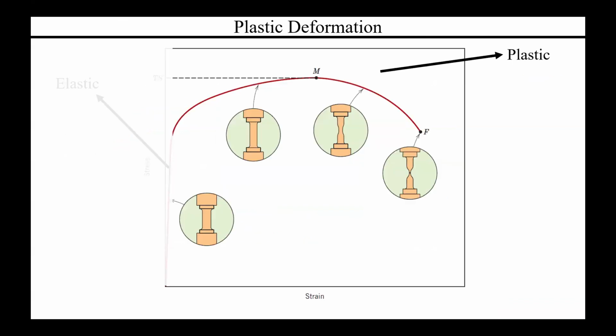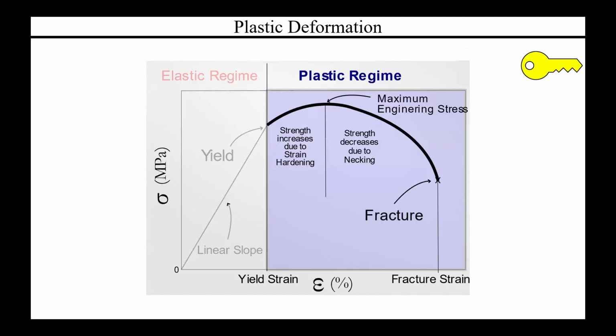So now let's move into the plastic region. The plastic region can be broken up into a few different zones. The first is, you've left your elastic region and you're pushing yourself towards this M point, or tensile strength. We'll talk about it later. That is where you're seeing a uniform deformation within the material. Past that point, you're getting localized deformation. So that's why you're seeing this hourglass shape start forming in the pictures. That essentially means that the stress is concentrating within those specific points. And what you're actually seeing is a phenomenon called necking, where, again, that stress is highly localized to a specific region, and that is the region where the material will ultimately fail. And that failure is the point F, or fracture point.